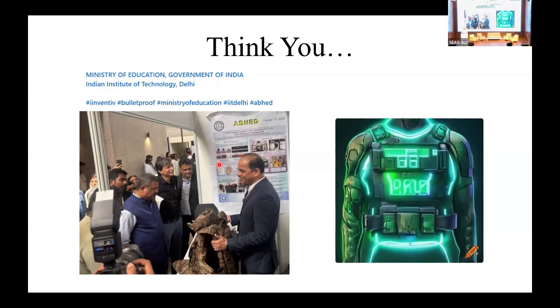I request those who are students, if anyone is here, and if you happen to find a piece of glass somewhere in the scrap, place it away, try to strike it, record it, and let's try to see what is the speed of propagation of the crack, how fast the glass breaks basically. So we attempted and we found that we require even higher speed cameras. It is going in lakhs, but we can't measure that, with the facilities we have, we couldn't. But we did see that first this crack goes out and then circles are formed. So circumferential and radial is clear, but speeds are to be measured.